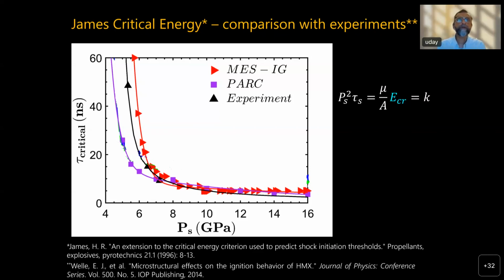Yes, I certainly do actually. So if you look at where we are, about 5 GPa, 5 GPa is about the pressure at which we find that most of the voids are sort of borderline. They're not collapsing in full hydrodynamic mode. And if we do the calculations of that, in fact, with the Johnson-Cook model, the rate dependent model, and so on, that you guys actually have published on, Kyo, we find that there are shear bands, and there is a significant change of mode of collapse of the void. Whereas for high pressures it's hydrodynamic, in the jetting mode, for the lower pressures, it tends to be more of a closure mode. In fact, as you go to lower pressures, it closes with a sideways pinching mode rather than a jet mode. And in the sideways pinching mode, the shear bands play a very large role.